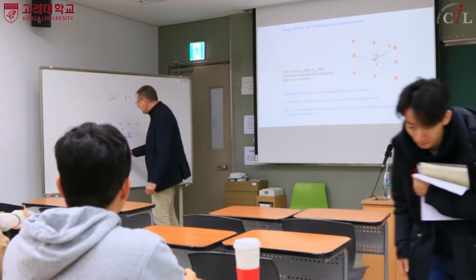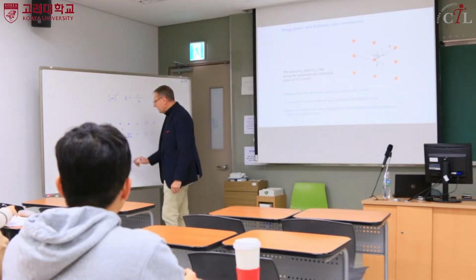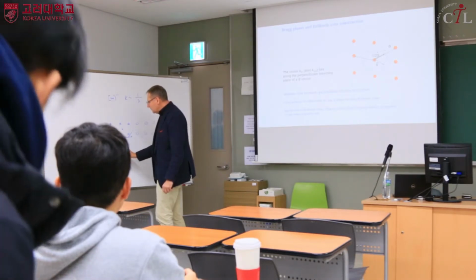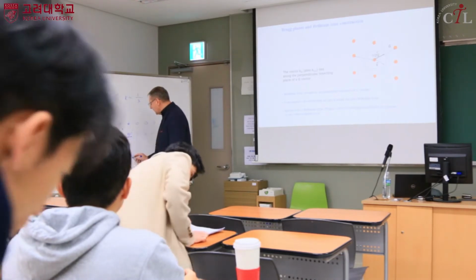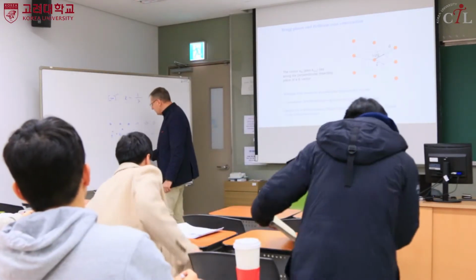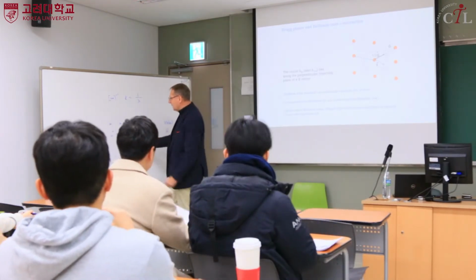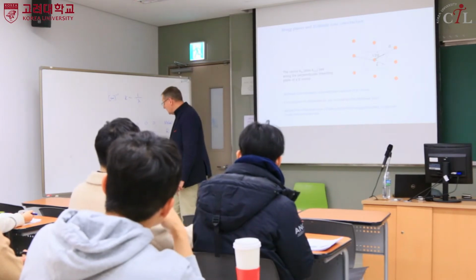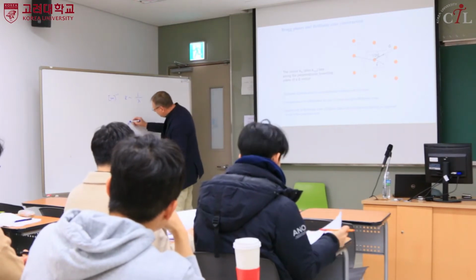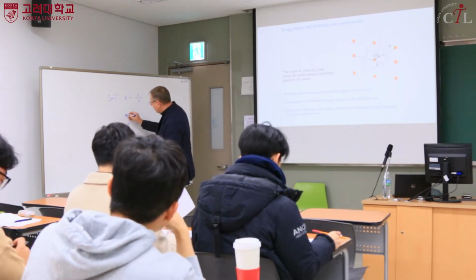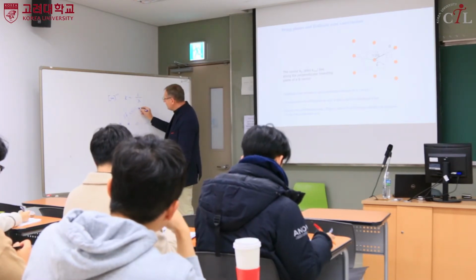If you make a measurement of electrical resistivity, you can get a value that will bring you to the idea that the mean diffusion path, let's call it lambda, the mean distance the electron can go without collisions, is some 1 millimeter. It's very huge, because the distance between atoms is some 5 angstrom or something like this. So 5 angstrom is much, much smaller than 1 millimeter.